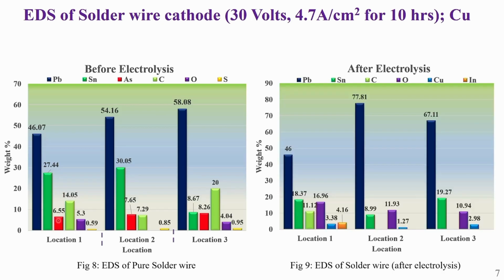The right figure shows the EDS analysis of solder after electrolysis. In the blue color bar, there are 3.38, 1.27 and 2.98 weight% of copper at location 1, location 2 and location 3 respectively. We can clearly see copper as the transmutation after electrolysis, which is not present in the initial sample.